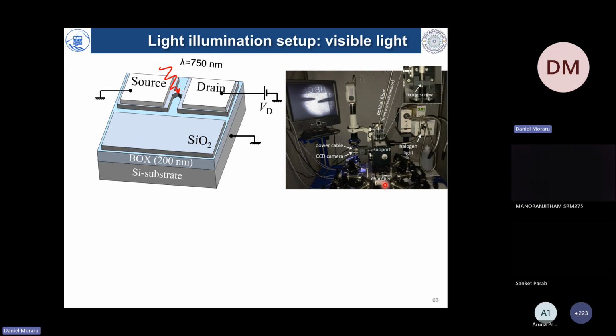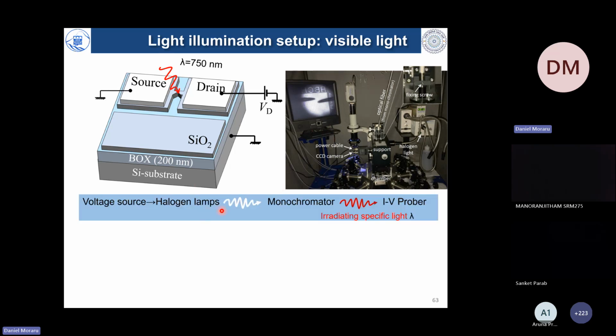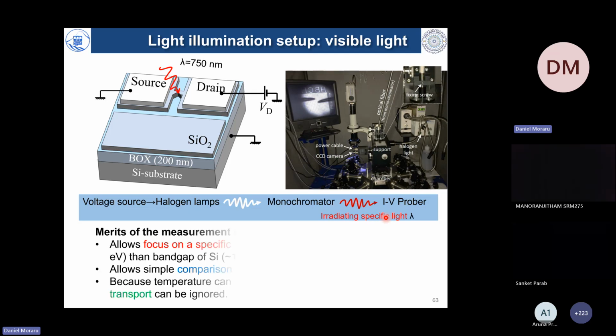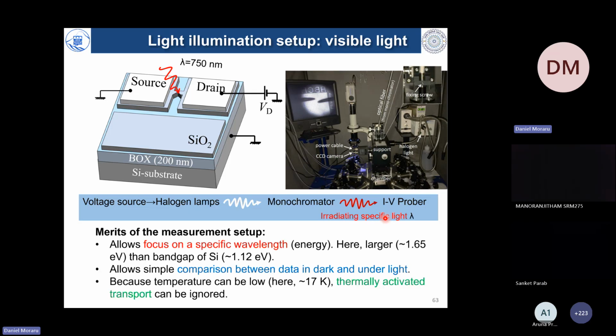We put our samples inside this metallic chamber under vacuum at low temperature, but we also irradiate light through this support system and through an optical fiber and shed it on the sample, with the probes connected to the appropriate pads of aluminium. A halogen lamp is used, but a monochromator cuts off the specific wavelengths, and that allows us to focus on specific energies of the photons.